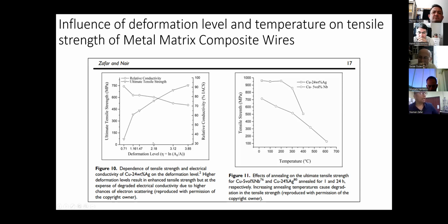Okay. I have shown you the influence of temperature on the tensile strength. It was decreased. Here is a picture from my paper in which I have reported 2 different composite wires. And indeed, they have also reported a decrease in the tensile strength after the temperature. Again, for the reasons which I have just told you, grain coarsening, rearrangement of the grains and formation of larger grains. And here, increasing deformation levels have caused an increase in the ultimate tensile strength of the wires. This is also taken from the literature. So my results are not completely in disagreement with the literature.